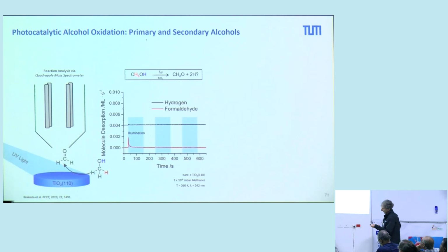You have here titanium without clusters, and we expose this to methanol, and then you illuminate this sample with photons. And you see a little amount at the very beginning of formaldehyde, almost no hydrogen. Then we stop the light, we turn on the light again, and you see nothing. That means we poison the surface. We have an initial amount of formaldehyde that is formed, but then the catalyst is dead.